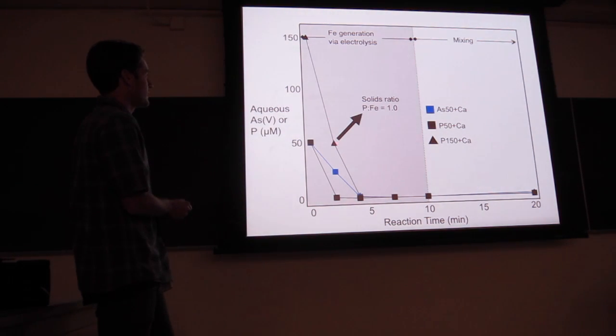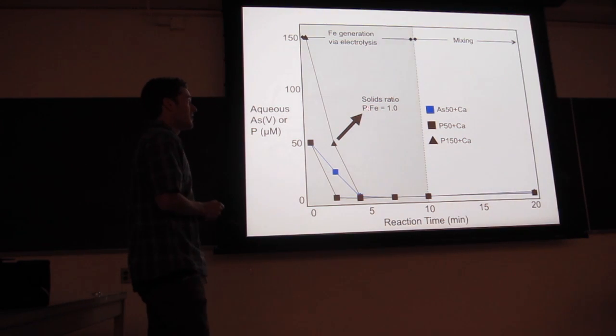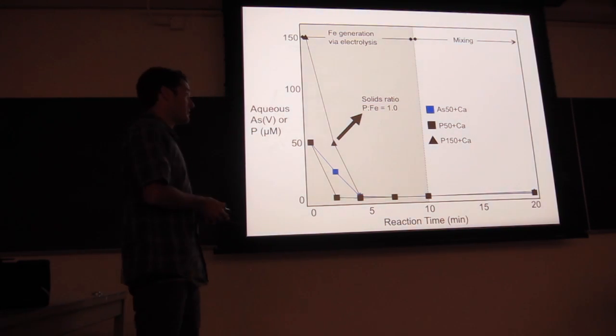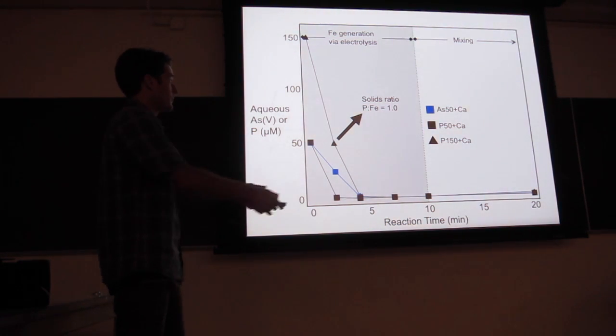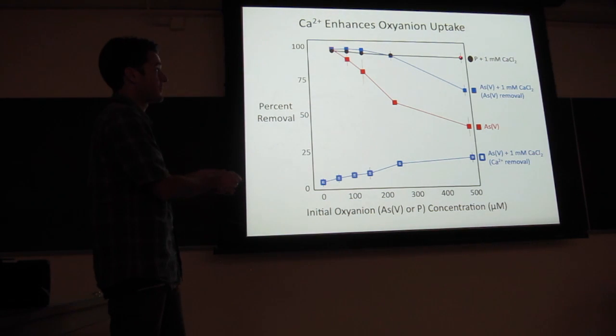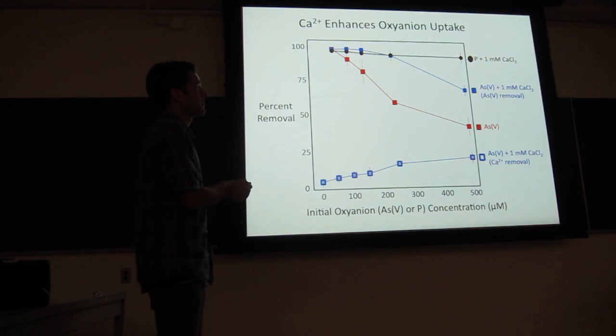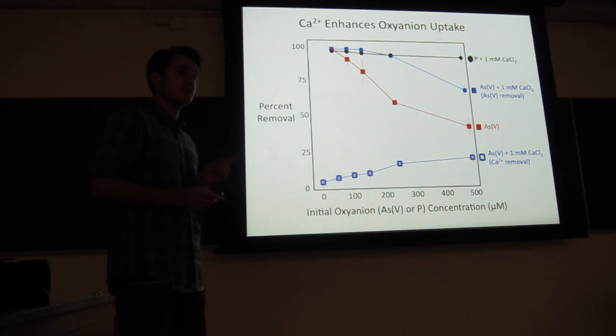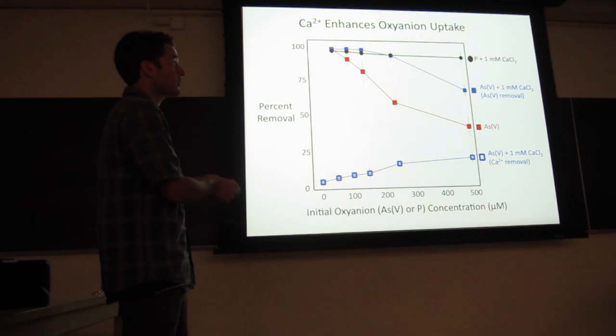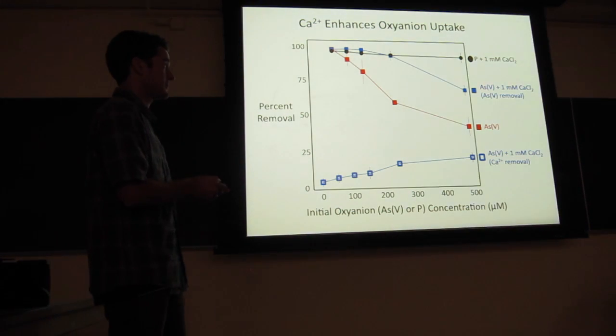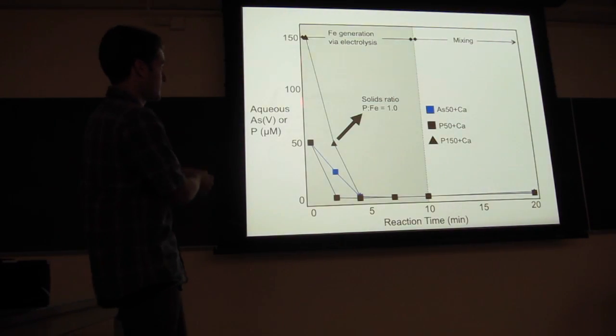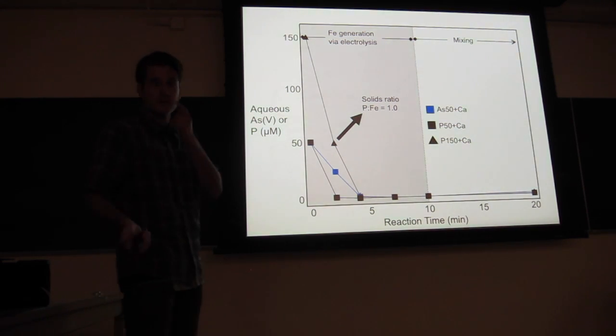Going from here to here, in 2 minutes, the solids that are generated here have a solids ratio of about one phosphorus atom for one iron atom. And that's exactly what we see in this sample here. So we expect that the structure of these samples can serve as a good approximation for the structure of the samples that are formed here at the onset of electrolysis.